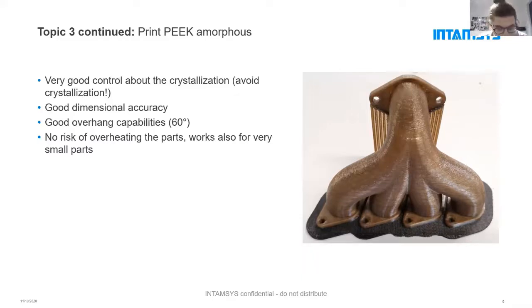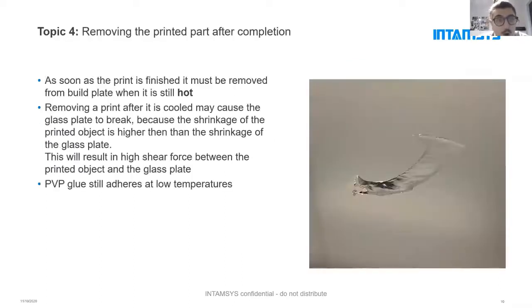If you then decide, okay, I will go with amorphous printing, and your print is finished, you should consider when you remove your part after completion. First, it's very easy to say, we do recommend to remove the part in a hot state. If you don't remove the part in the hot state, you have the risk that your part has more shrinkage than the glass plate. And when you then still have adhesion from your glue, you definitely get a lot of shear force. And in the end, you can get broken glass plates. So we do recommend to remove it in a hot state